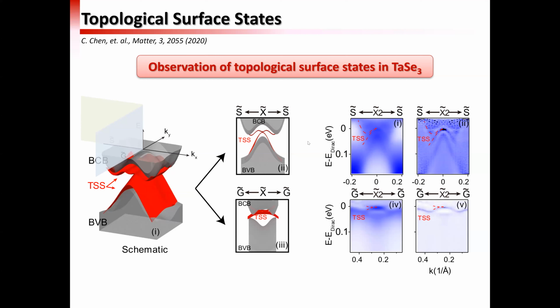Of course, the superconducting temperature of this material is so low, it's 1.75 Kelvin, so our current ARPES spectrometer cannot go down below that. So we were not able to tell whether the topological surface state got gapped. That's why we claim this material as a topological superconductor candidate. And then we encourage the transport colleagues to study this, because the transport temperature can go well below this.